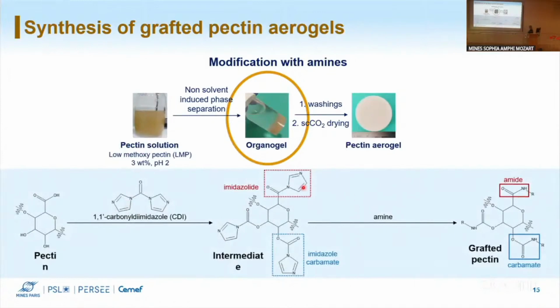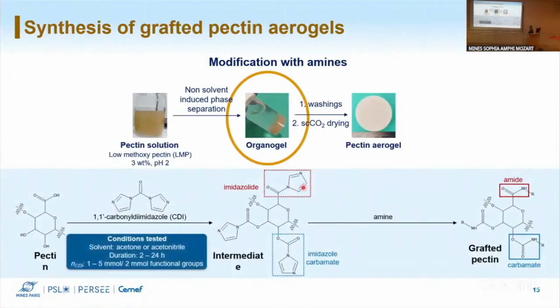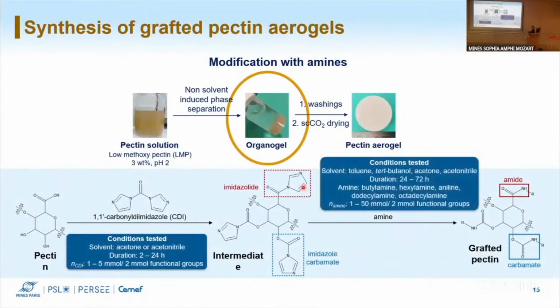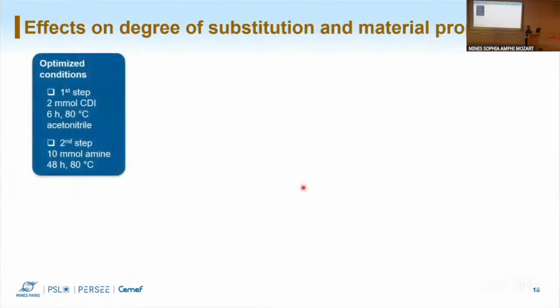We varied a lot of parameters for this reaction. So first we varied solvent, duration and amount of CDI. And for the second step, we varied again the solvent, the duration. We used 5 different amines and also the amount of amine that was used. So first we optimized the conditions. We did a lot of test experiments, and we used the conditions that are mentioned there for the further studies.